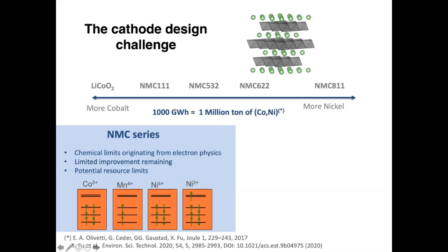And there are, first of all, chemical limits to them, that there's a reason they're called NMC. They contain nickel, manganese, and cobalt. And that's pretty much the only elements you'll ever see in these layered materials. And that comes from their electron physics, that if you make a layered material, if you pull the lithium out, then in many cases, transition metals want to migrate into the lithium layer.